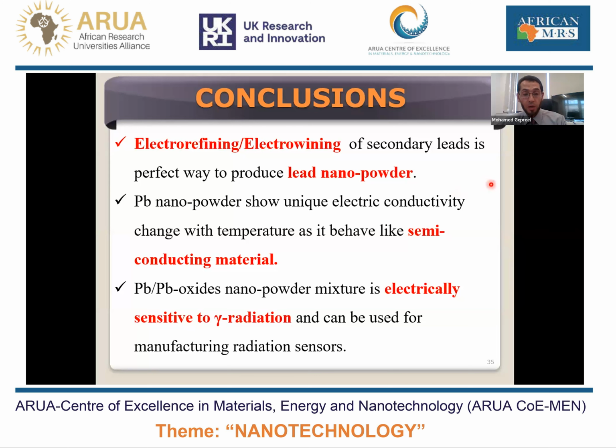I go to the conclusion that electrorefining, electrowinning of secondary lead is a perfect way to produce lead nanopowder. Actually, we are the first to do this technique, and lead nanoparticle powder shows unique electrical conductivity change with temperature, as it behaves like a semiconducting material. Lead oxide nanopowder mixture is electrically sensitive to gamma radiation and can be used for manufacturing radiation sensors.